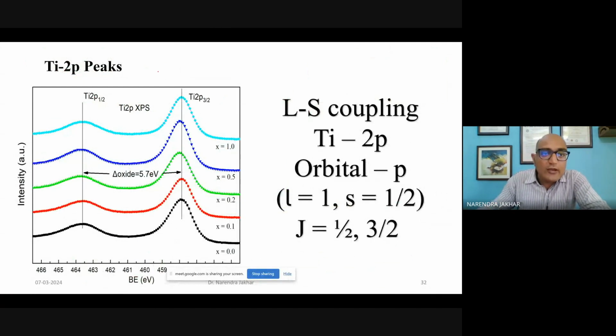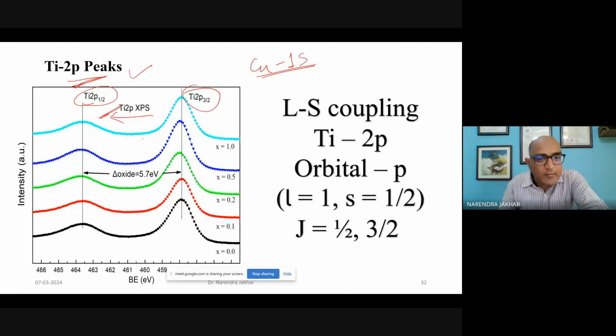And this is Ti2p again. So in this case, in the survey spectrum, you have not seen Cu1s, as we already talked about. Again, here you got Ti2p. In the same sense, Ti2p 3/2 and Ti2p 1/2. Ti2p 1/2 is on the higher binding energy side, and a characteristic of these oxides is that the separation between the titanium oxide peaks is 5.7 electron volts.